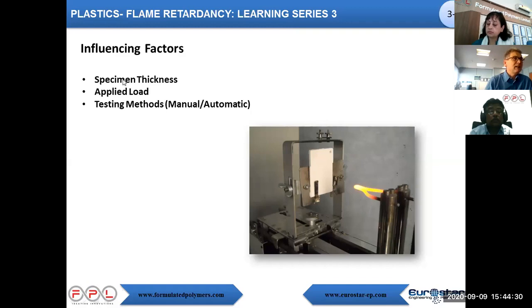Influencing factors are specimen thickness. This is especially true for the glow wire flammability index, because the wire goes through the plates, and the time to go through the plates is the time that the wire heats the material. It's less important for GWIT, the ignition temperature, which is more a surface-related measurement, because you are measuring the interaction between the fire and the plastics. The applied load is fixed, you cannot change it, and the testing method can be manual or automatic.